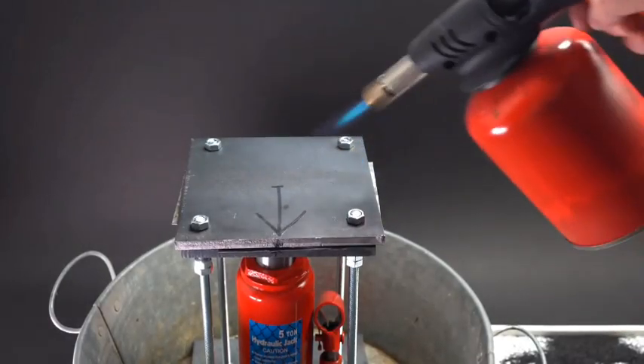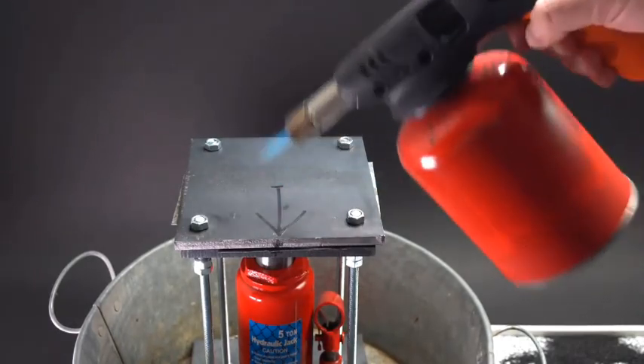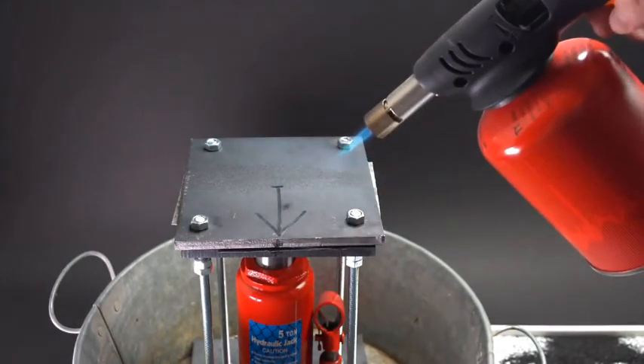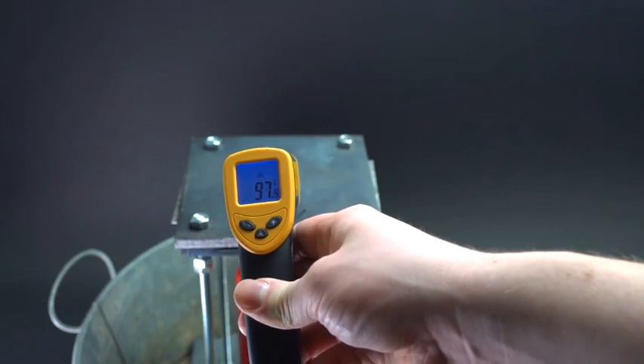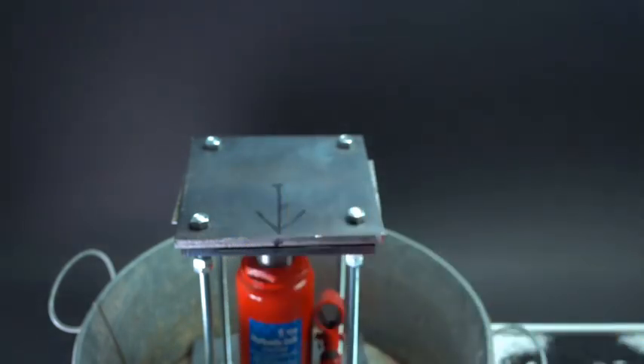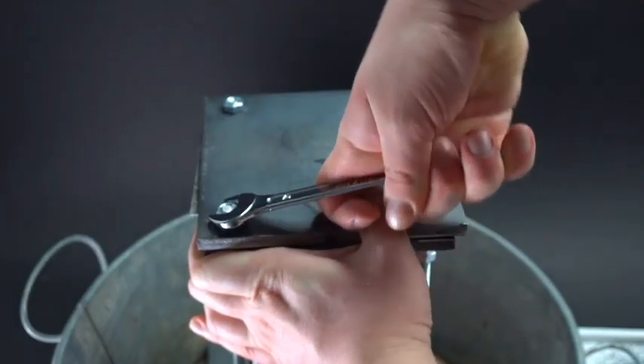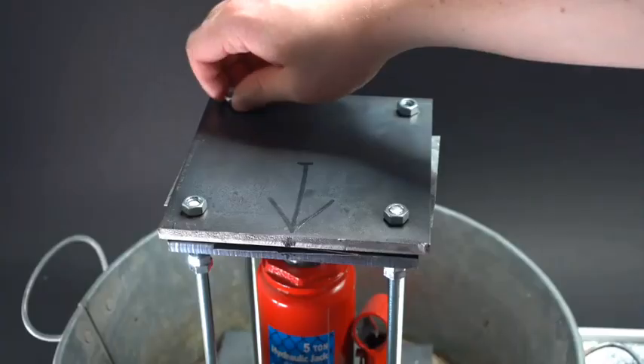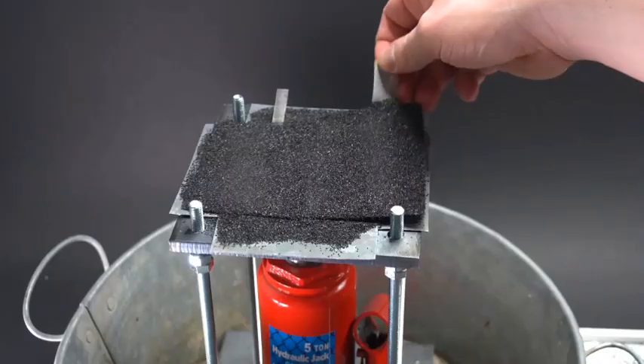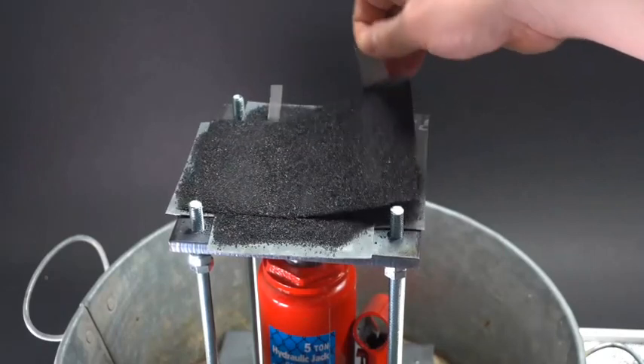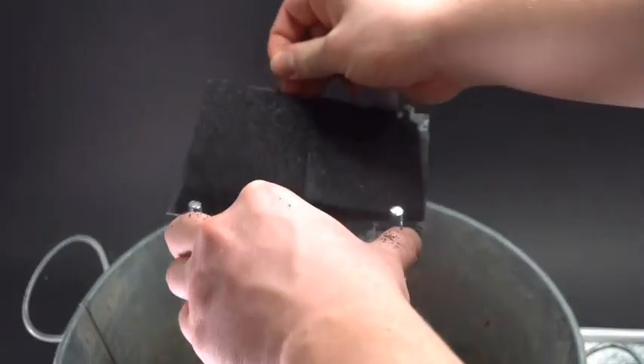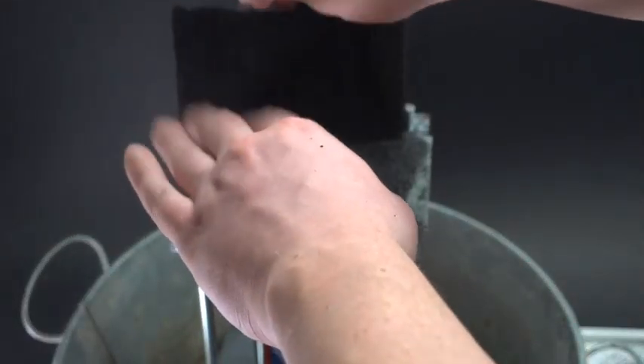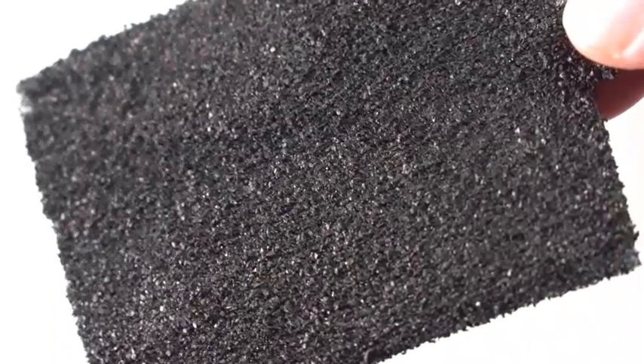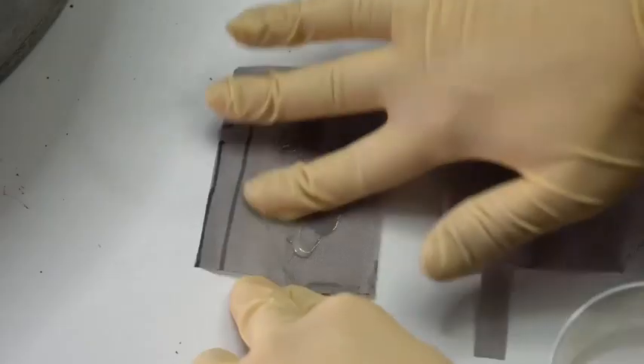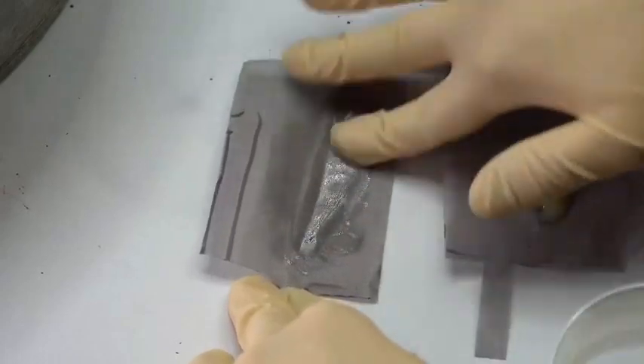However, if you cannot wait so long, then you can speed up the process by heating it up. I am heating up the place with a burner to about 100 degrees Celsius. Then I leave it out like this for 40 minutes. In 40 minutes it hardened, and then I could loosen the nuts and check what I've got. Generally speaking, it looks quite good. Now I have 2 freshly made cathodes. After that I need to make 6 more for my experiment.